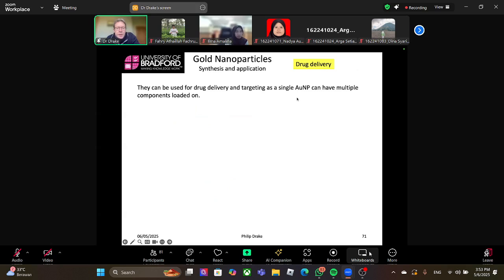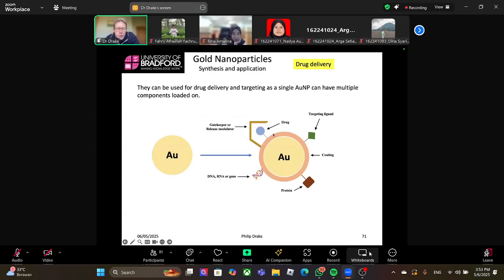You can also use it for drug delivery. So a gold nanoparticle, as we saw, was big. Because it's big, you've got lots of options for adding different things to the surface. So you can add in a drug molecule. You can add in targeting ligands. You can add on DNA and RNA. So you can modify the surface of gold nanoparticles with lots of different components all at the same time. So you can make very good drug delivery systems where the nanoparticle carries a high concentration of drugs into a cell, and you can then have some kind of mechanism where the drug is then released from the particle within the cell. So they're very good for thermal therapy. They're also very good for drug delivery systems.